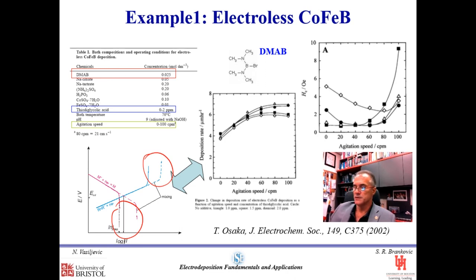Also, you can see that more mixing also results in more boron incorporation into the deposit, which makes the deposit soft to a certain extent. However, after we reach a certain point, more mixing no longer contributes to the positive properties of the cobalt-iron-boron, because too much boron now starts to actually increase the coercivity of these materials.